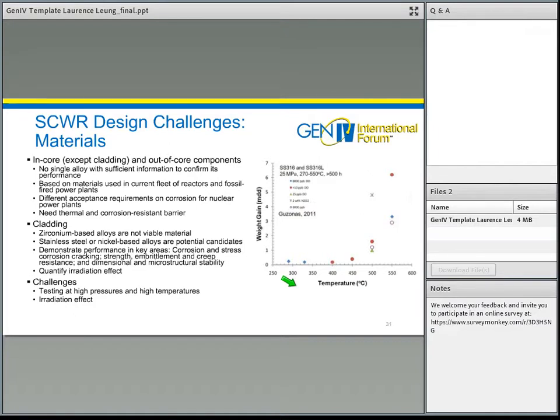Because it's a high temperature, high pressure reactor, one of the challenges is to get the material. For the in-core and out-of-core components, what we find is no single alloy that has sufficient information to confirm the performance for use in the SCWR components. But we can adopt a lot of information and experience from the current fleet of reactors and fossil fuel power plants. And we have to establish different acceptance criteria or requirements for corrosion in a nuclear power plant. And because of the high temperature operating condition in the core, we probably need a thermal or corrosion resistant barrier for components that have a very high temperature gradient.